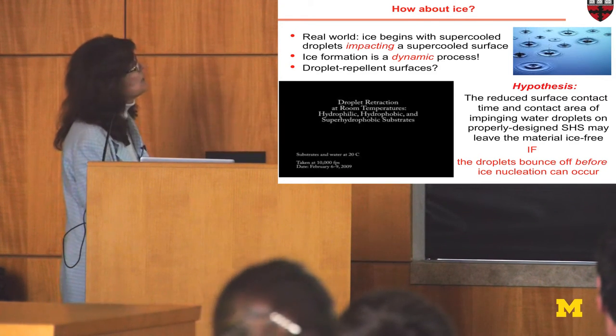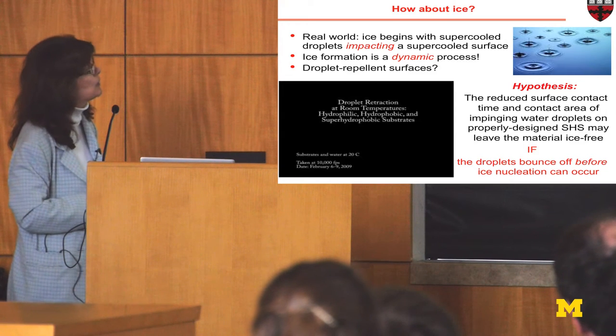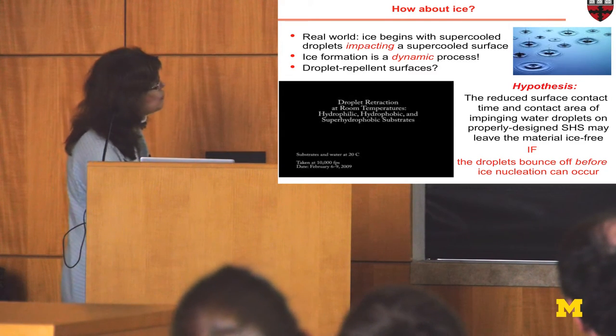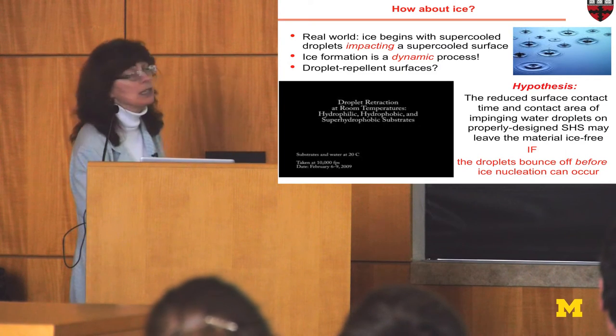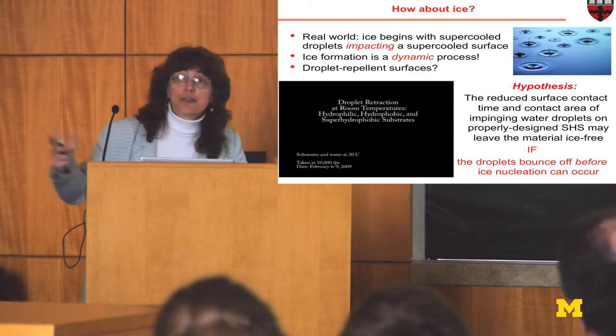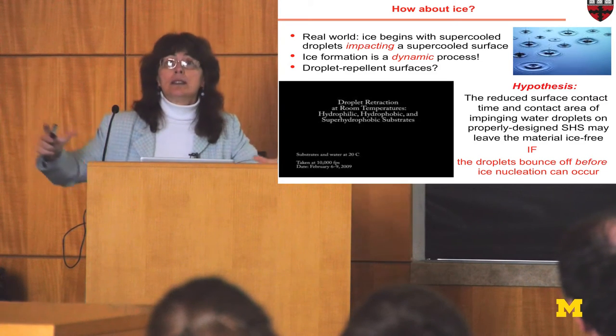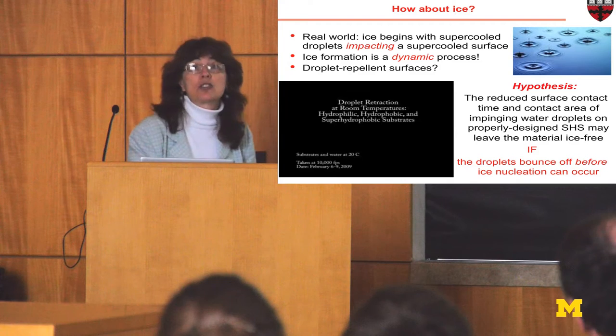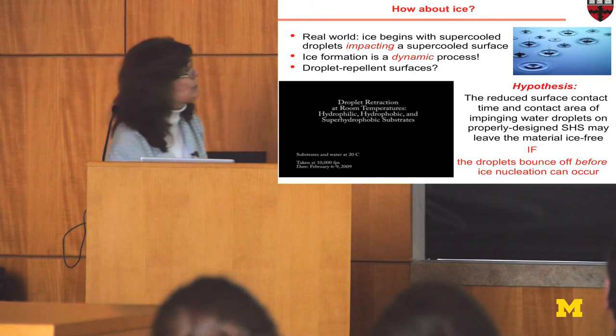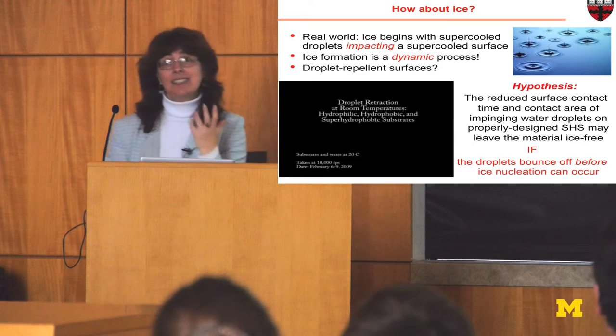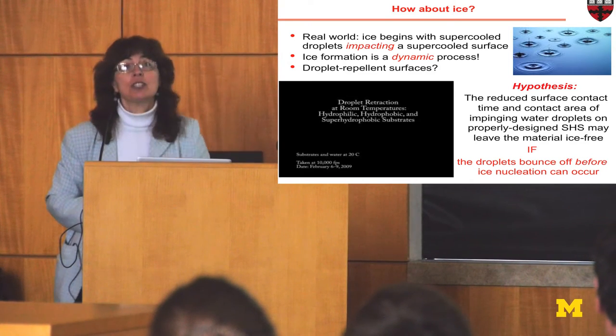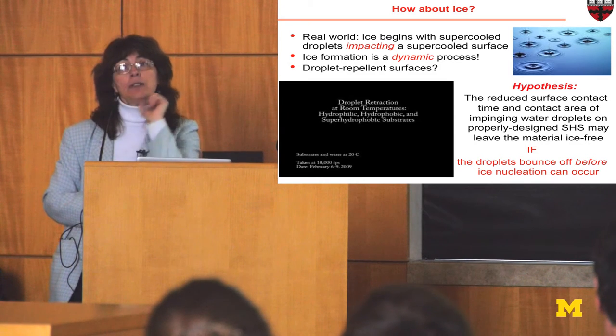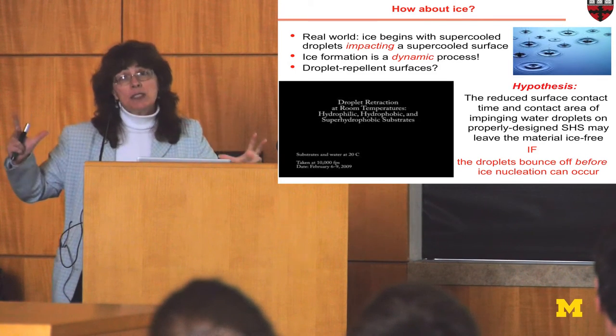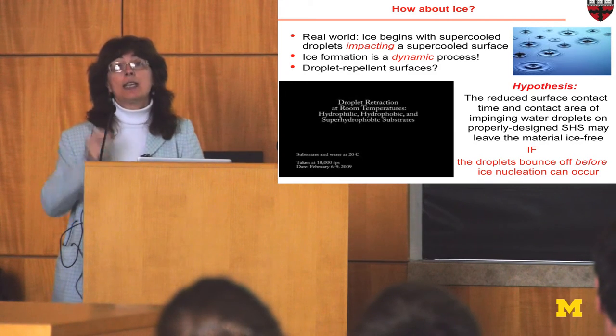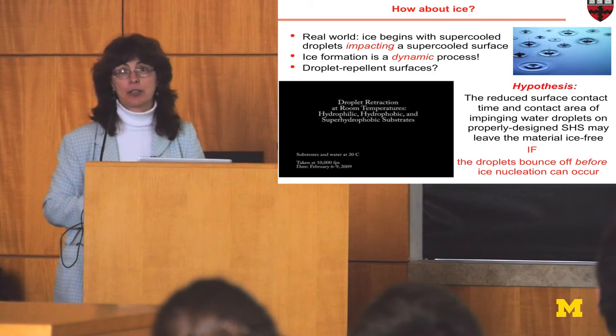But maybe, if we think about it as a process where there is impact of droplets on the surface, maybe due to the fact that superhydrophobic surfaces have the ability to be almost a friction-free surface, the droplets spread rather than being expelled from the surface. So as a crystallographer, I was thinking that there is always a delay in nucleation. There's an induction time for nucleation. If we can build these surfaces in such a way that the time it takes for the droplet to withdraw from the surface is less than the induction time for nucleation of ice at these conditions, ice will not be formed.